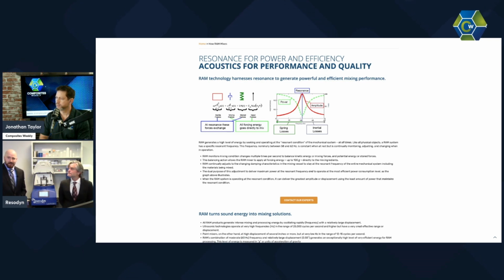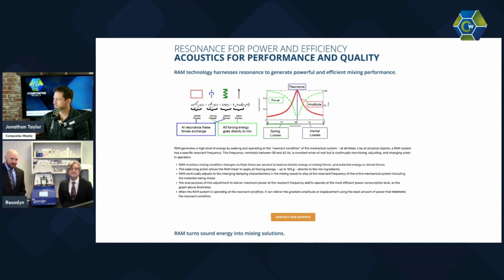Another application that's kind of out there is, we're really good at dissolving rubbers and polymers into solvents. We have a synthetic rubber manufacturer that has multiple lab RAMs worldwide, where they're using RAM in their QC labs. They have these continuous synthetic rubber manufacturing lines, and they take a sample off that line and test it in their QC lab. They basically dissolve the rubber into a solvent. They were using horizontal shakers originally, and it was taking about 6 to 8 hours to get a result to gauge the quality on that line. When they switched to RAM, they were able to get a result within 15 minutes. So it's saved them a boatload of money, and also on scrap material too.